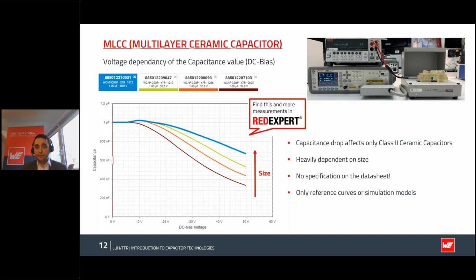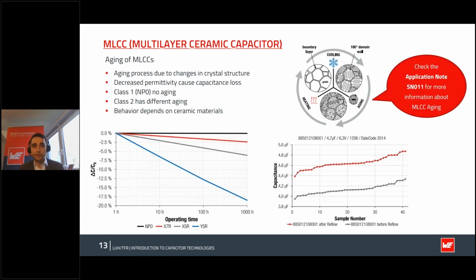Apart from the DC bias effect, there's also the aging of this MLCC. For this, I have the graph on the left to show you. Here you can see the line in black is an NP0, so a class one ceramic. You can basically see over 1,000 hours, it has no loss in capacitance, so pretty much no aging. When you go down then to the red line is an X7R ceramic, which is a highly stable class two ceramic. You see over 1,000 hours, it has about 2.5% in capacitance loss.